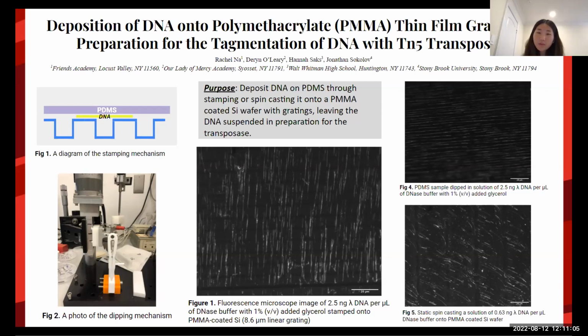Results indicated that PDMS that was cured in a 60°C oven for 2 days increased the adhesion of DNA on the PDMS. However, this made it difficult for the DNA to be stamped and transferred onto the silicon wafer. The salt also made it difficult to transfer the DNA, causing the DNA to rip. To solve this problem, glycerol was added instead of salt to aid transfer. Figure 3 shows one of the most successful results we've had.